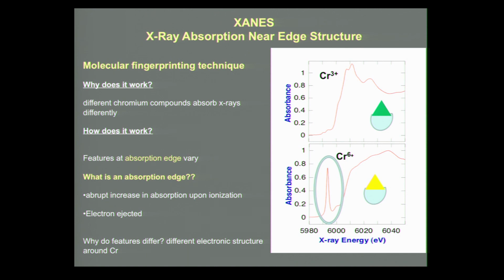And what happens is that when a compound absorbs X-ray energy, so we're looking at increasing X-ray energy in this direction, there's going to be these spikes in absorption when the atom in the compound is ionized, or when an electron is kicked out from that atom. And these spikes in absorption have certain characteristic features for different chromium compounds, and so you can see these little wiggles after the spike in absorption called the absorption edge for chromium 3+, and you can see this strong peak before the absorption edge for chromium 6+. And so even just looking at these two plots without really knowing what the wiggles and the spikes mean, there's no way that you would confuse one for the other. They're very characteristic of the different chromium compounds.